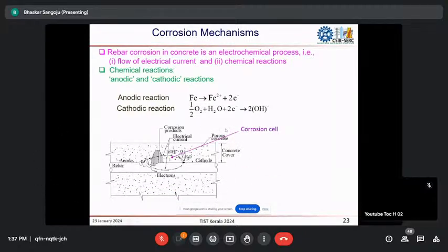If you see this line sketch of rebar embedded inside, depending on the quality of cover concrete, voids or honeycombs and cracking, those places may become a cathode, where oxygen and moisture will be present. And if there is any variability in the material, anodes will form. At the anode the electrons get liberated and try to move towards the cathodic side, because the electrons liberated have to be consumed, otherwise there will not be any reaction to continue. So the important thing is that we can arrest either the cathodic formation or the anodic formation.